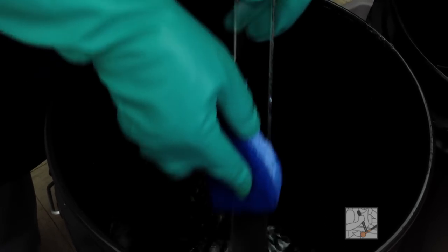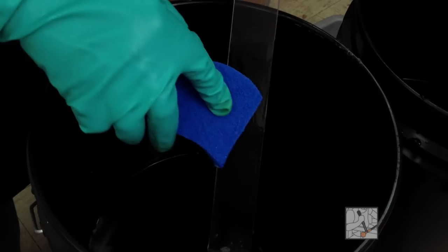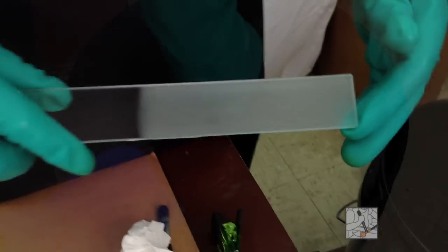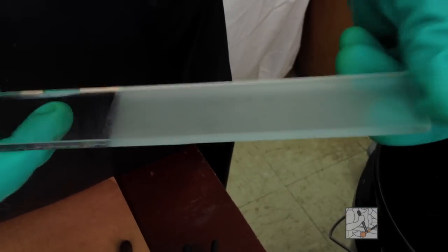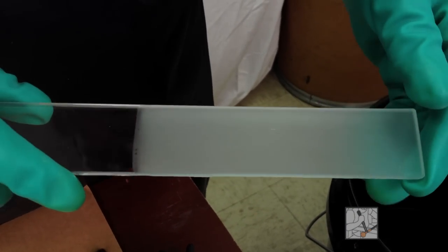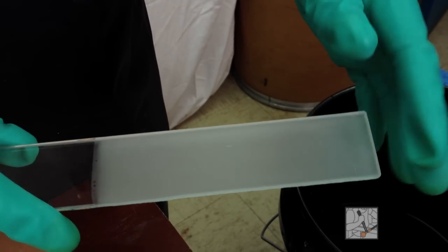You can see the bubbles. That shows you that it's working. You should clean your glass. You want to wipe off all the glass that was etched away. It will remain in contact with your glass as a kind of filmy scum, and if you touch it with your gloves, it will feel quite slippery. And then into a clear water rinse. You can see that it's nicely etched. I noticed the scratch on my glass before I etched it. That did not go away. So you want to make sure your glass is just the way it should be, nice and clean, free of scratches, marks, dirt, whatever.